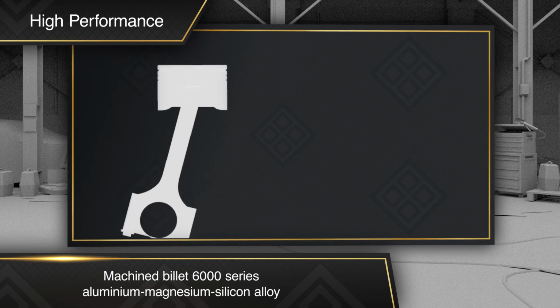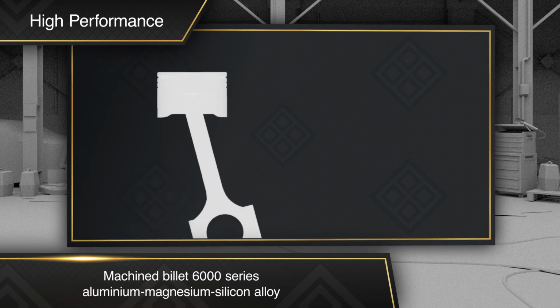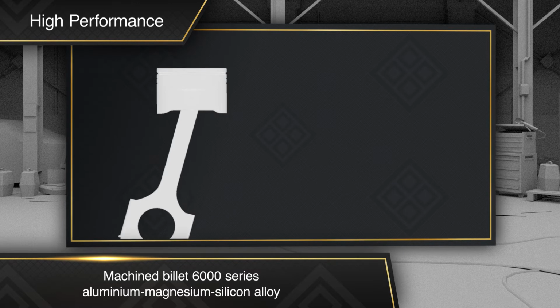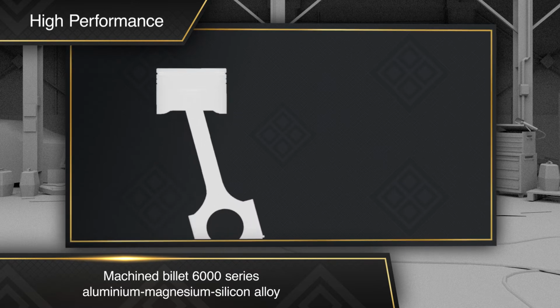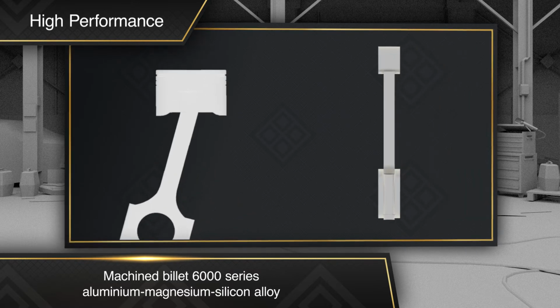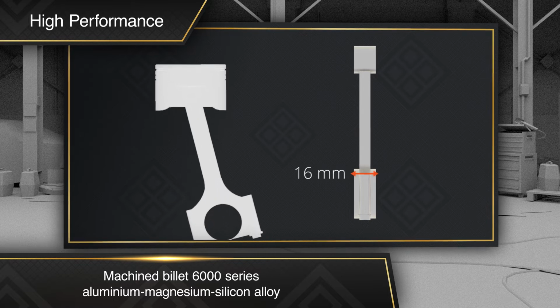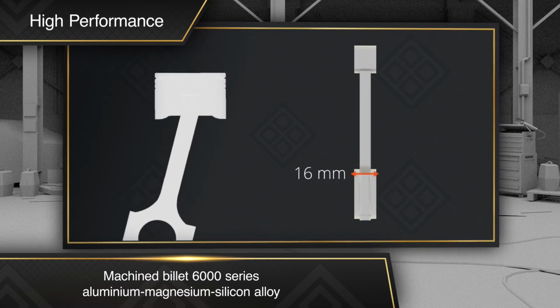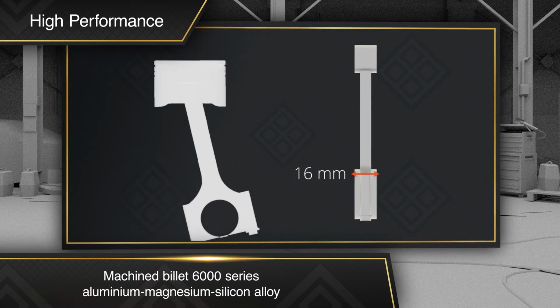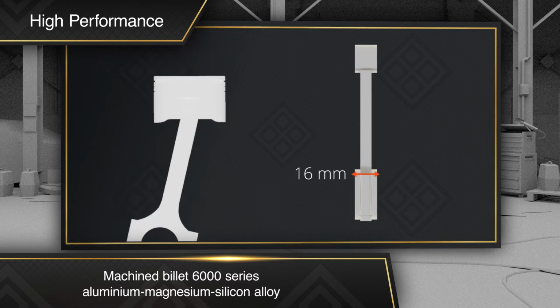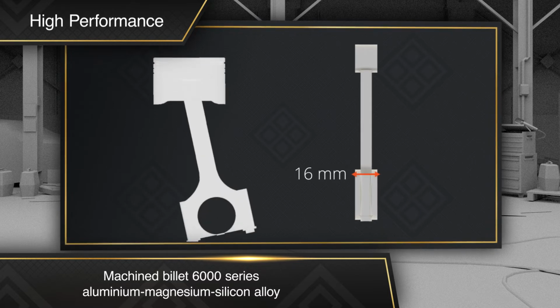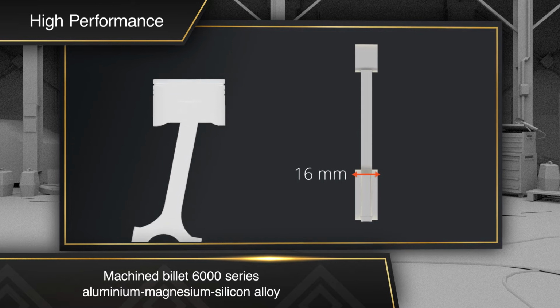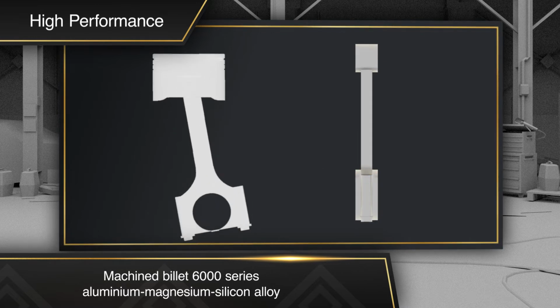although for high-performance engines, machined billet 6000 series aluminium magnesium silicon alloy may be used, where the lower strength and stiffness compared to steel is offset by thicker material from around 12 mm up to around 16 mm, although at greater financial expense, while still benefiting from a 20 to 30% weight saving, and while the limited fatigue life is justified by the willingness to replace the connecting rods more frequently, although again at greater financial expense.